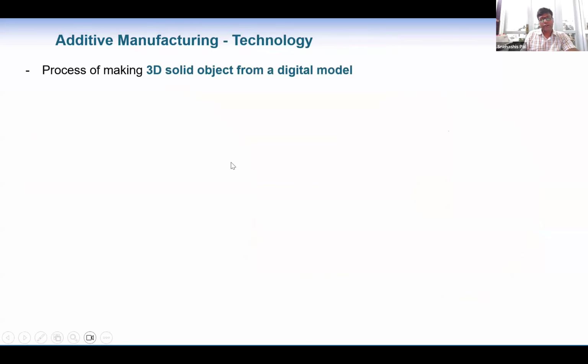Correct. So in the additive manufacturing process, it's a process of 3D printing. I mean, going from a 3D digital model to the real one. It's actually done layer by layer. It can be a micron-size layer, let's say tens of microns, to maybe sometimes more, depending upon the technology. For metal powder bed systems, we use more or less 20 micron to 100 micron.